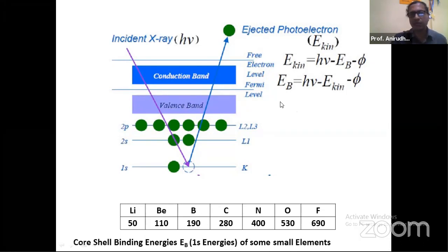So when people calculated those binding energies for different materials, which I have shown in the table below, for lithium, beryllium, boron, carbon, nitrogen, oxygen, fluorine, etc., they found that the innermost electrons, the binding energy related to the 1s electrons, which are the core electrons, the electrons closest to the nucleus, the 1s binding energies of different elements are distinctly different. Say for example, the 1s binding energy for lithium is 50. For beryllium, it is 110. Similarly, it is 190 for boron, 280 for carbon, and so on.